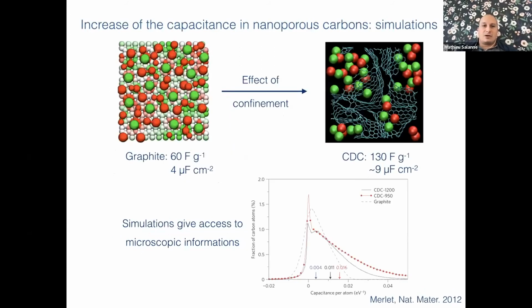So then what we try to do first is to understand the effect of confinement. What happens when you switch from a planar electrode like graphite towards a nanoporous one? And indeed, we observed a similar effect as in experiments, because we had an increase of the capacitance by a factor of almost 2. You need, of course, to normalize your results either using the mass or the surface. But in both cases, we see the same increase. And so we have something that is consistent, again, with the experiments.